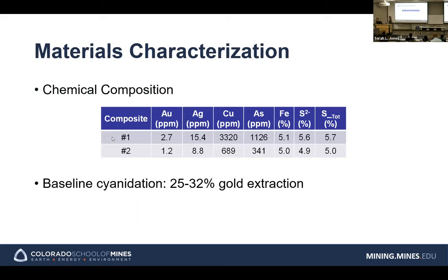So that's the chemical composition of the sample. The gold grade for number one is 2.7 and for number two is 1.2 grams per ton. It's not high grade, but not bad, 1 and 2 grams per ton. There's a little silver, copper and arsenic. As you can see, sulfur is 5%, 5.6% and 4.9%. So those are the typical sulfide grades in refractory sulfidic gold ore.